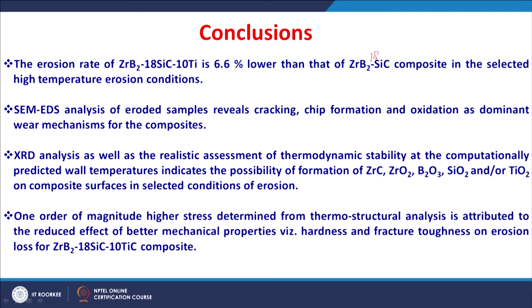The eroded samples reveal mainly the cracking, the chip formation and oxidation as dominant mechanisms of material removal for the composites. X-ray diffraction analysis as well as the realistic assessment of the thermodynamic stability at the computationally predicted wall temperatures indicates the possibility of the formation of several phases: zirconium carbide, zirconium oxide, boron oxide, silicon oxide or titanium oxide on the composite surfaces in the selected conditions of erosion. One order of magnitude higher stresses are determined from the thermostructural analysis.